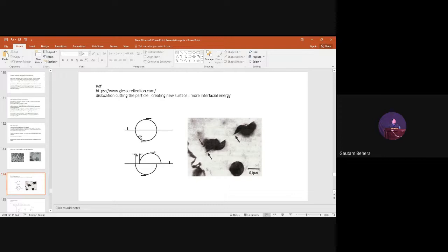Right? Initially, this is the only surface available. An interface is there in between the matrix and the precipitate. But now a new, additional interface is created. That leads to an increase in the interfacial energy. And once the interfacial energy increases, the dislocation cannot move easily. It will get restricted and you need more stress to move the dislocation.